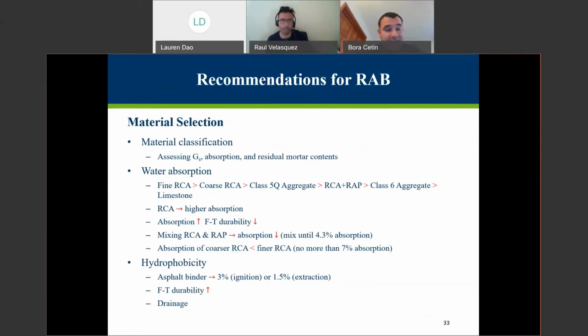And for the hydrophobicity, again, to be on the conservative side, you may want to use the ignition method, which is a little bit faster to determine the asphalt binder contents too. And one thing that we realized is that by adding RAP, you're increasing the hydrophobicity, so aggregate material became water repellent, doesn't want to suck water in much. That would impact the freezing, improve the freeze-thaw durability a little bit more.